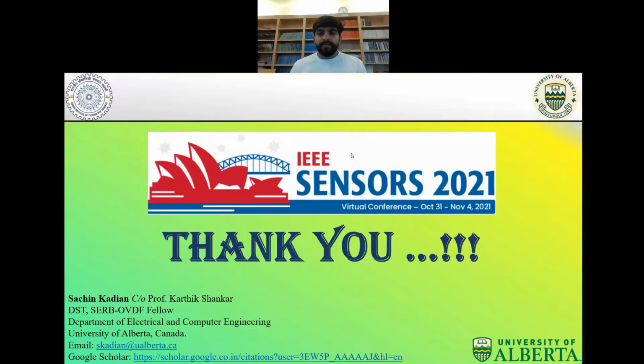So, the conventional fluorescent sensing probes have already used organic dyes, that is, porphyrin. And the performance of an optical gas sensing probe is highly dependent on the diffusion of analyte fumes into the sensing platform. Therefore, due to porosity and good accessibility of the gaseous analyte in the sensing material, micro and nanostructures such as nanoporous fibers, micro nanoporous films, and honeycomb films have widely been used as a substrate matrix for the incorporation of this organic dye and development of this gas sensor.